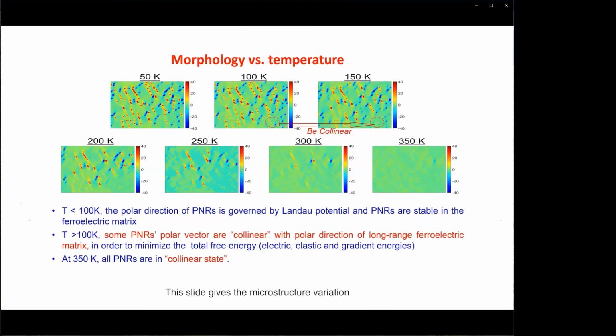This slide gives the microstructure variation with respect to temperature. At temperatures below 100 Kelvin, each polar nanoregion almost keeps its original rhombohedral phase. This is governed by the Landau energy. With increasing temperature, the difference of Landau energy between the rhombohedral and tetragonal phase will decrease for polar nanoregions. Thus, in order to minimize the total free energy, polar nanoregions will start to transform to the tetragonal phase. This means that the polar vector of polar nanoregions is collinear with the polar vector of the ferroelectric matrix. We call this state of polar nanoregion the collinear state. As shown here, at 350 Kelvin, all polar nanoregions are in the collinear state.